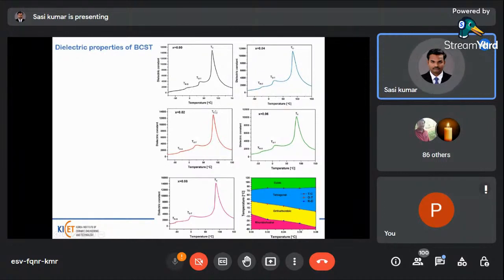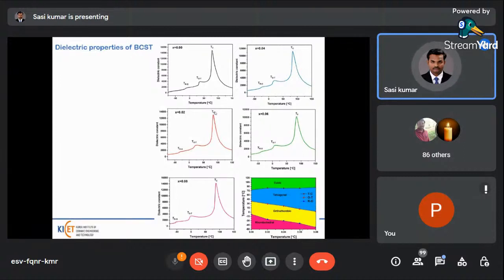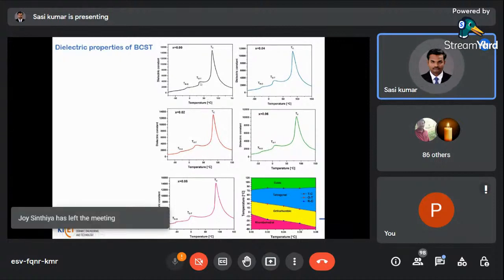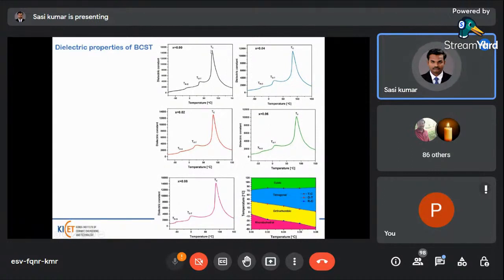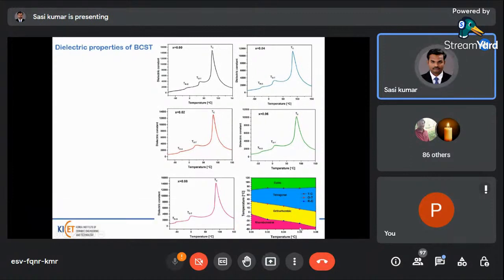There are three different dielectric anomalies. First one is the rhombohedral to orthorhombic phase transition, another one is orthorhombic to tetragonal phase transition, and finally tetragonal to cubic transition, which is termed as the Curie temperature. And then using all these transition temperatures, here I plotted the phase diagram of this composition.